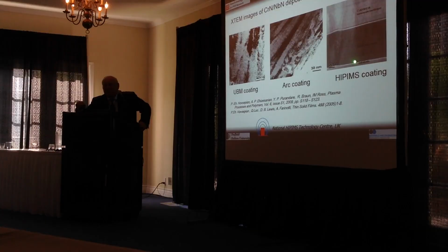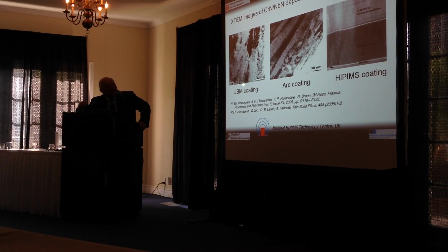So a big difference can also be seen in the coating structure. This is a chromium nitride niobium nitride nanoscale multilayer deposited by unbalanced magnetron sputtering, arc evaporation, and hybrid. With technology which provides very low energy of the arriving species on the substrate, you often see these voids and very wavy layers. Arc is perfect, it gives you very good interfaces, but arc will also generate a droplet. It's a droplet inside of the coating, and you can see the defect which grows, and you can see the compressive stress in the coating, which is able to close these defects after 80 nanometers of growth.